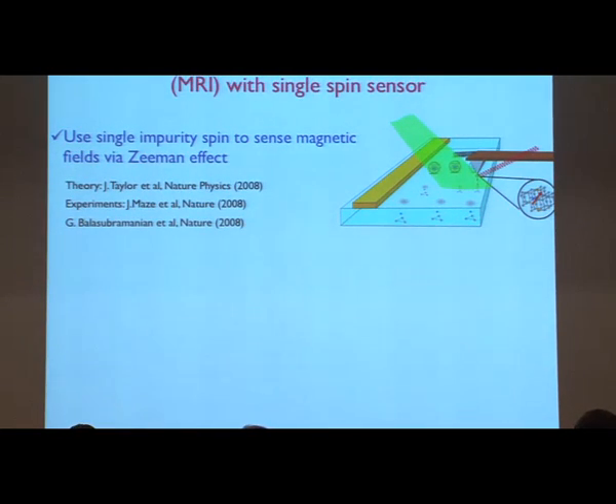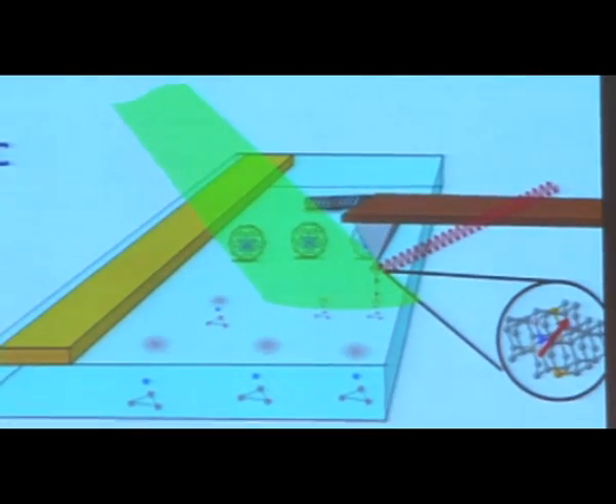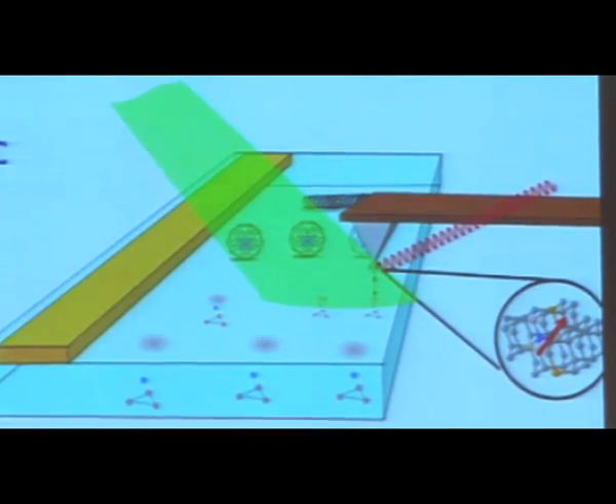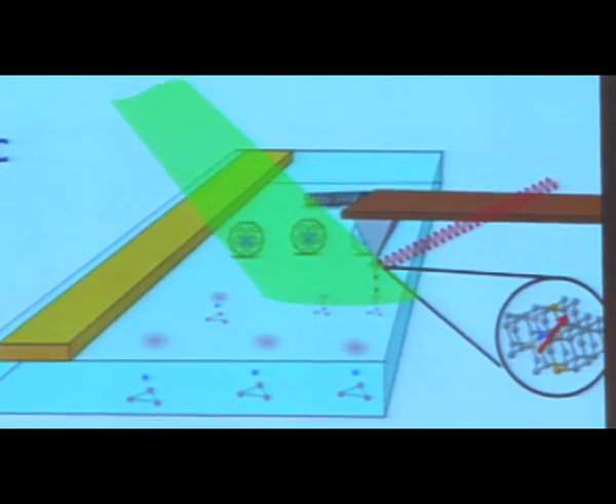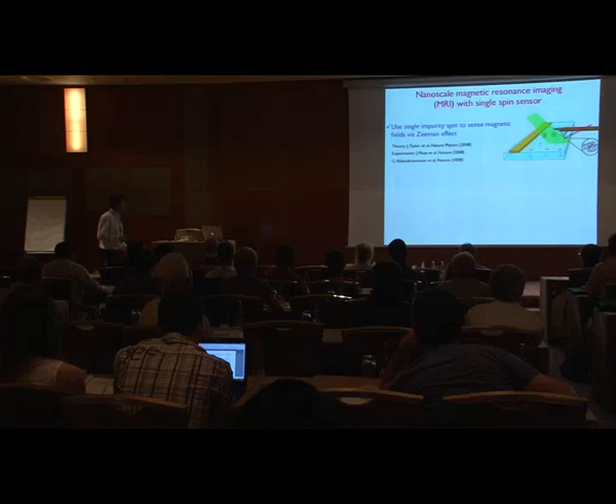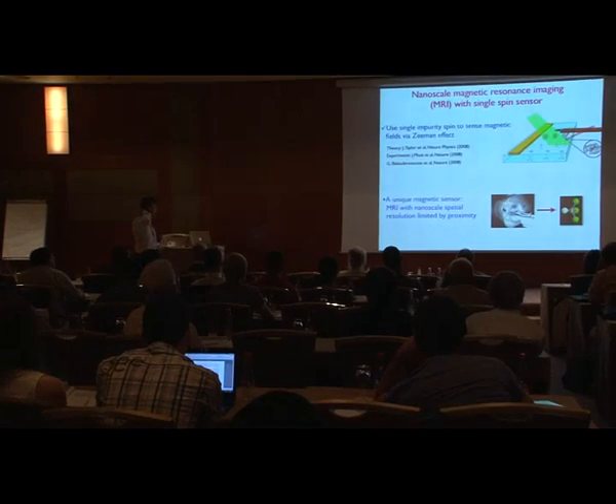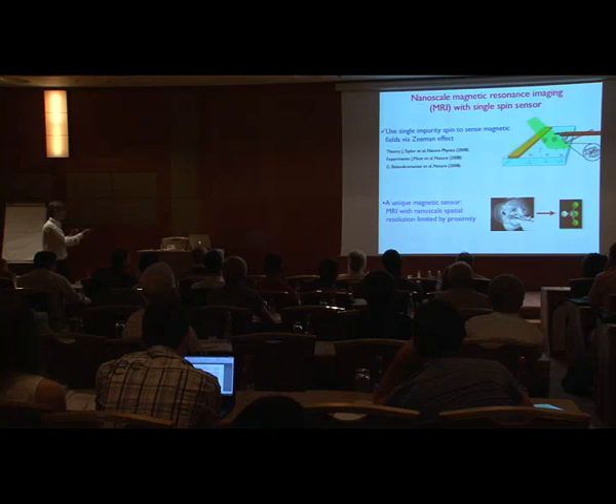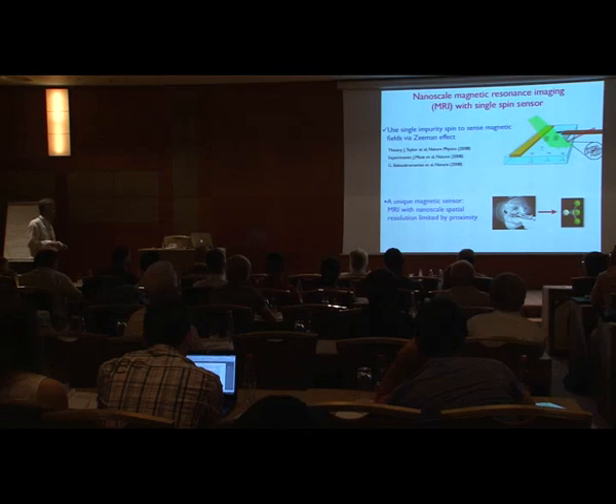In particular, it turns out that we can use a nitrogen-vacancy center as a tiny magnetic sensor, where it can measure the field from the surrounding environment just through the Zeeman effect. What happens is that the magnetic field changes the rate of the quantum evolution of the nitrogen-vacancy center. And this is remarkable because this sensor is very small, so it can be brought in direct proximity to very small objects like single molecules. This holds promise to extend magnetic resonance imaging techniques truly to the nanoscale.